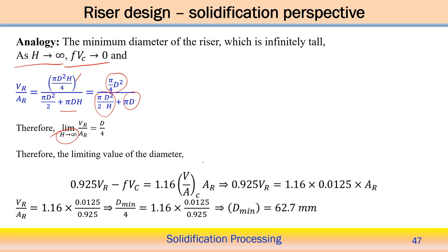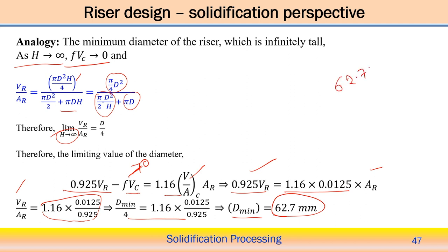So if you put the V by A of the casting in this case, the riser volume, we can calculate V by A of the casting, and in this case VR, because f tends to 0 here, and this we already calculated. So we can calculate AR in terms of VR: AR equals 0.925 into VR. Therefore we can see the VR by AR ratio value. It means that V by AR is equal to d by 4, d minimum by 4 equals C. So d minimum equals 62.7. So when you are taking the infinitely long cylinder, the minimum diameter should be at least 62.7, but the optimum diameter can be 98.2 millimeter.